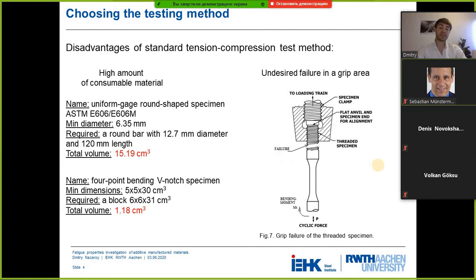Another problem is the undesired failure in the grip area. For example, when a tension compression specimen with threaded edges is not properly aligned with the main axis, it can cause the appearance of additional bending moments, and finally the failure could appear in the thread area. It's undesirable because we lose the priceless material, so this method is unacceptable. Therefore,